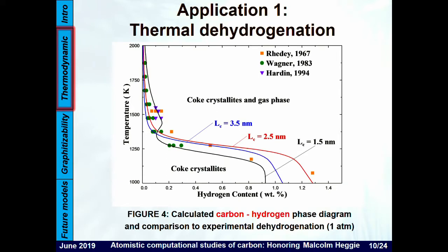After that, we can apply this model with the Gibbs energy software for the minimization of the Gibbs energy of the system. And here you can have the hydrogen content for a given value of Lc, which is about the same as La, of various coke crystallites as a function of the temperature of the heat treatment. So if you take a given carbon material and you heat treat it at this temperature, and if it develops this kind of Lc, you will have this hydrogen content in the system. And you can see this comparison with the experimental results, which is encouraging.